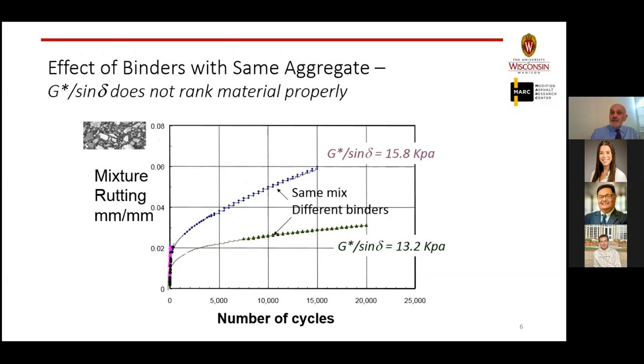Here's an example of data collected for rutting of asphalt mixtures. This is not binder data. This is the unconfined compression test. You can see these binders are approximately the same in G* over sin delta. In fact, the one in black or dark green is softer, relatively speaking, than the one in purple. However, when you look at the mixture rutting, it's totally opposite. It's so different that at 15,000 cycles, I have almost doubled the rutting for this binder that I thought is better than the one that I am using here.